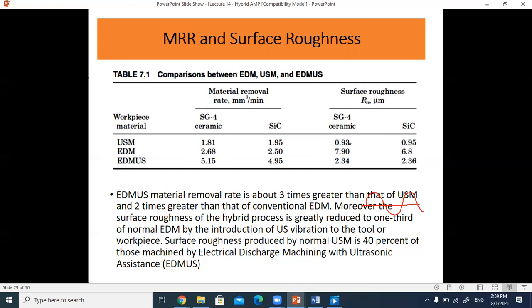So if surface roughness is critical for your process, then USM will give you a better surface finish. Worse is EDM, and then comes EDMUS, the ultrasonic assisted EDM process. In summary, in general, the material removal rate is much better in the ultrasonic assisted EDM process. However, in terms of surface roughness, USM is much better compared to the other two processes.